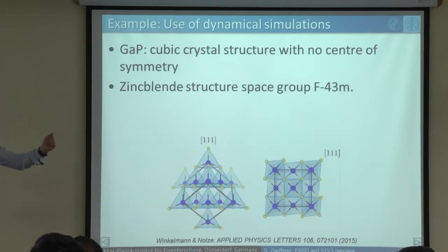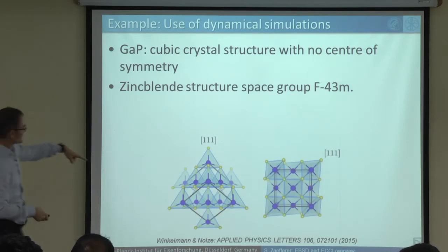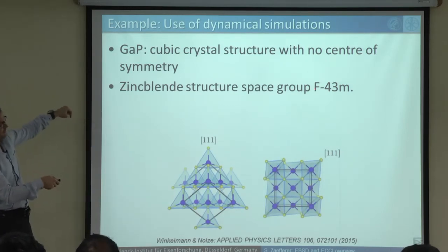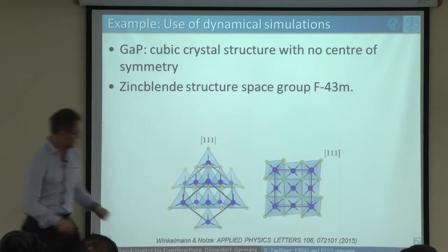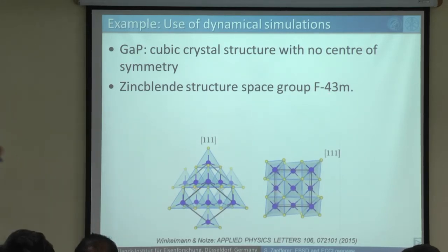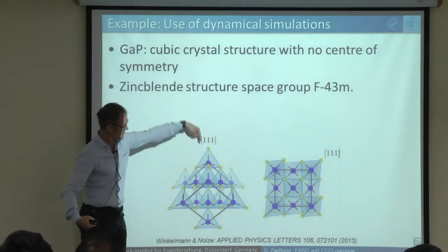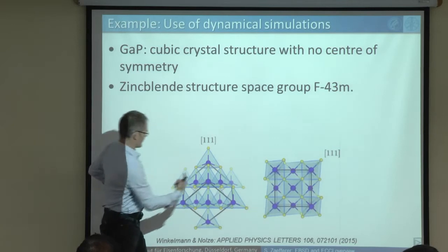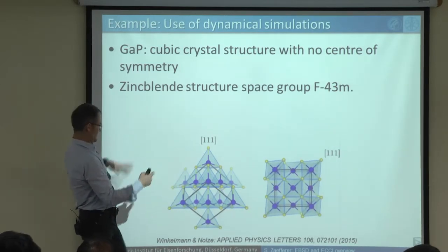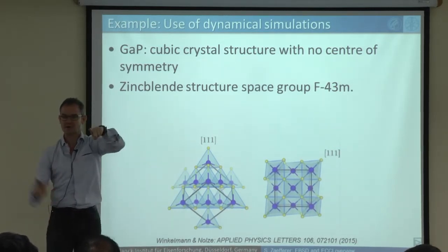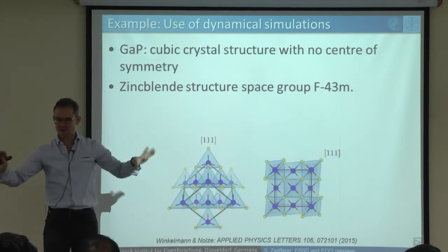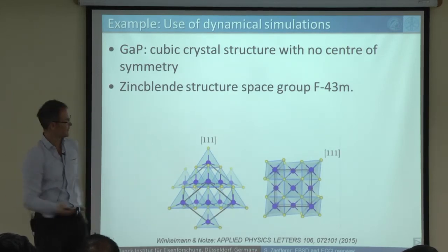So most of you are metallurgists, so you are familiar with FCC, BCC, HCP, and so on. All these metals have a center of symmetry in their crystallographic structures. But this one is zinc blende. The space group is F-43m, and this is actually without a center of symmetry. And that means if you're looking into the 111 direction or into the minus 111 direction, the things look different. This is not the case in FCC, for example.